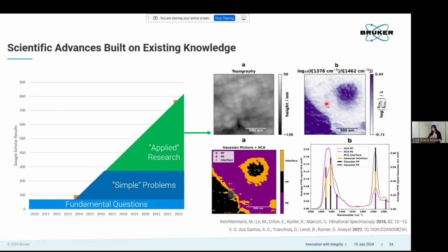But it goes a little bit further, and this is where we're getting into these questions of applied research of how can we learn really much more about the sample itself. And they start to do advanced computational analysis of this. And you see that not only are there two domains, but there are actually three domains. So there is one area, which is primarily polypropylene. You have one area, which is primarily polyethylene. And then you have this considerable crossover layer between polypropylene and polyethylene. This is important in this context because the mechanical properties of the post-consumer material are based on the chemical properties. And the fact that polyethylene and polypropylene are largely immiscible with each other weakens the plastic overall, which means that you're able to recycle it fewer and fewer times, and you get worse results each time you recycle it.